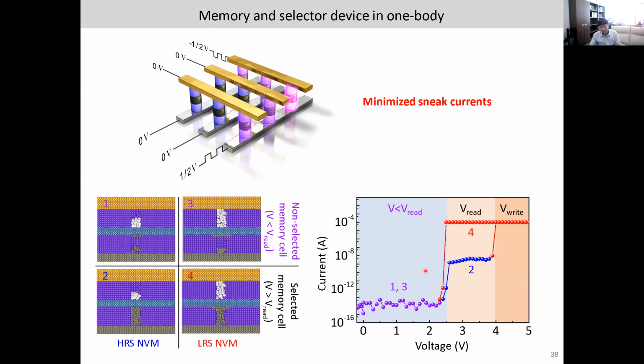And then for the non-volatile side, this is already well reported. I think at Soochow University in China, Mario Lanza, who has now moved to KAUST, suggested boron vacancy. Boron vacancies can be moved. So this is a graphene gold electrode, not a silver electrode. So boron vacancy can make this 1 state and 0 state.